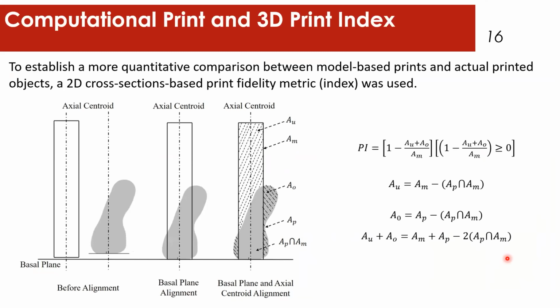Now, to establish a more quantitative comparison between the model-based prints and actual printed objects, a 2D cross-section based print fidelity index was calculated by overlapping the actual printed object or computationally printed object with the idealized object. So this is an idealized object and this is a computationally printed object. First I align the basal plane and then I align the axial centroid. Here I penalized for anything that is outside the idealized object and anything that is not covered inside the idealized object, and measured the print fidelity index from 0 to 1, where 0 is worst or not printed at all and 1 is the perfect object that matches the idealized object.